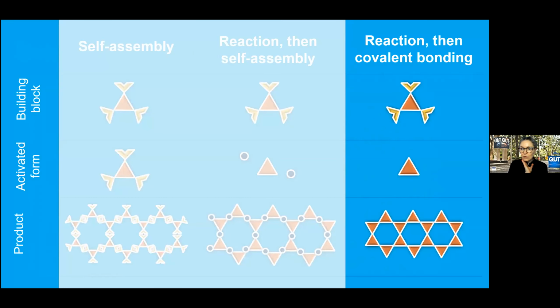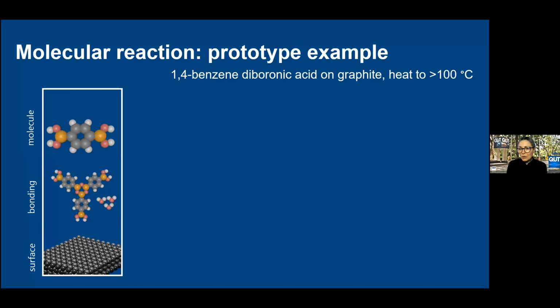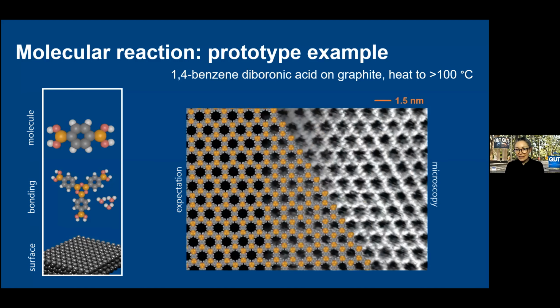Interestingly, we can also look at reaction, then covalent bonding on inert surfaces for reactions where we don't need to catalyze the chemistry. And the prototypical example that I'll show you here is a polycondensation reaction. The molecular building block is 1,4-benzene diboronic acid, which we can deposit onto graphite or graphene, and we heat it to about 100 degrees or so. And what you can see is that the boronic acids lose essentially water molecules. The molecular byproduct here is water, and this condenses our linear molecule into almost exactly the same architecture that we saw from TMA.